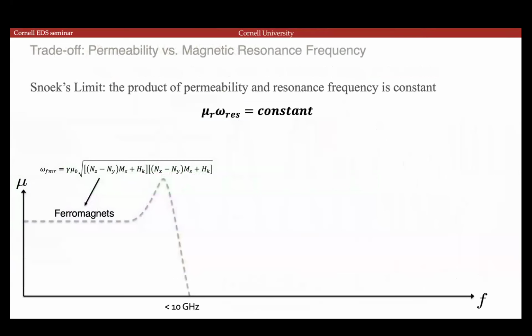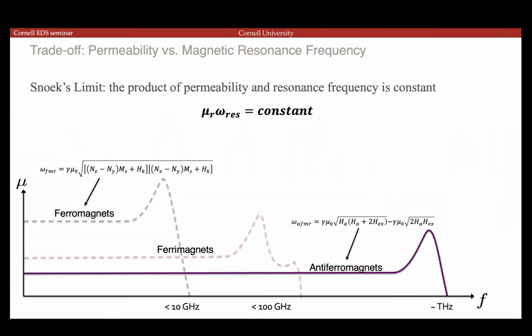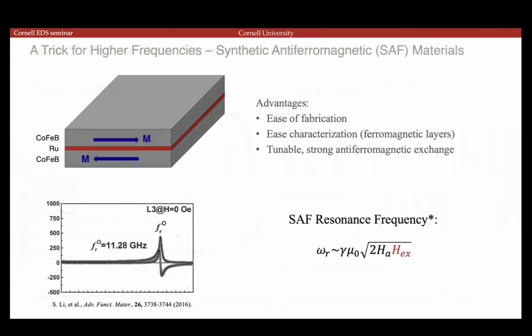So the one consequence of switching to other types of materials, though, is that there is a direct trade-off. As you increase the resonance frequency, the permeability will decrease. So the amount of the contribution that the magnetic material can provide to the system also goes down. We're aiming primarily in the 10 to 30 gigahertz frequency range for now for the new devices for 5G and 6G electronics.